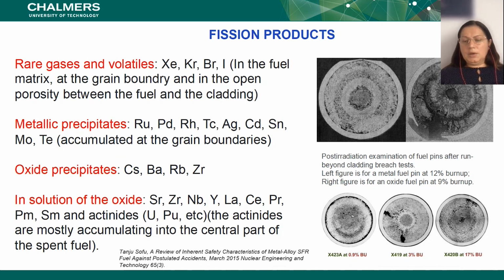So basically, they will go towards the center part of the fuel after higher burnup, so irradiation for a long time in the reactor. So you see that it's very easy to actually follow and see and to know where these phases are. And knowing this, you also can judge which one of them will come out first, and what phases, what chemistries they will form when they are coming out and meeting the coolant. So this, of course, is very important because this way you also know the time it takes for these to come out, and also how they can be released further into nature if there is an accident with an open reactor site. So it's not the containment, it's not intact anymore.